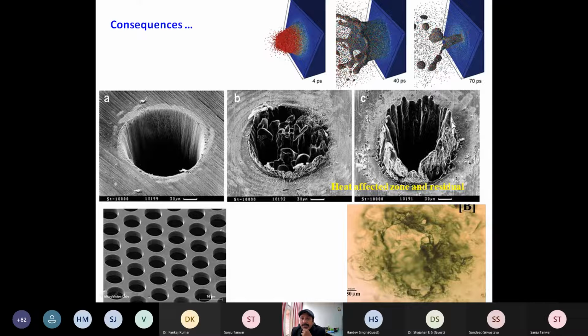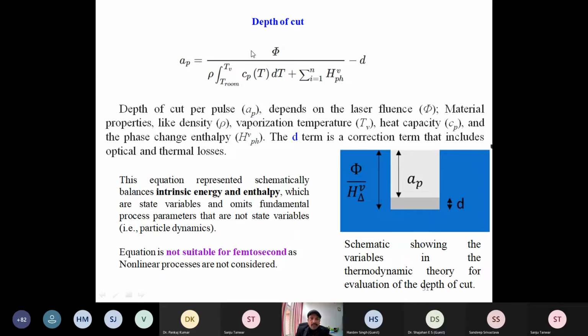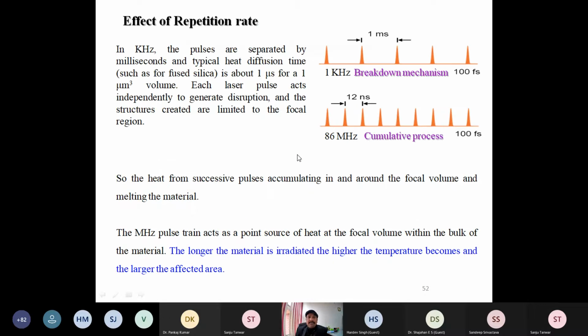Here somebody used a nanosecond laser, here somebody used a picosecond laser, and this one is a femtosecond laser. The residual portion is very less in case of femtosecond laser, and in nanosecond it is too much. This is the case with glass. We did this bored glass, and you can see some residuals redeposited near the surface. Now this becomes very difficult to clean, so some chemical is again required. This is the formula that we use for nanosecond, to estimate the depth of the ablated crater.